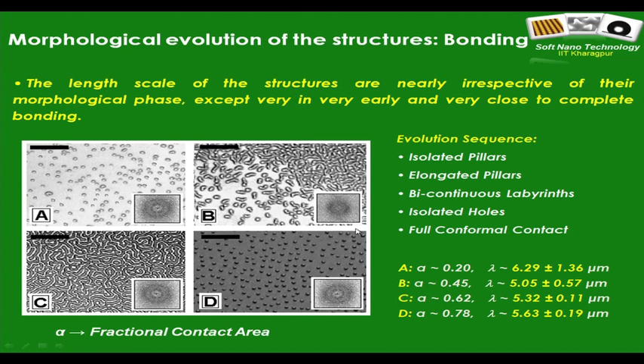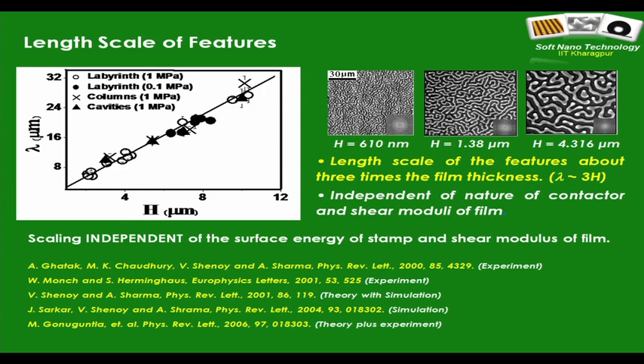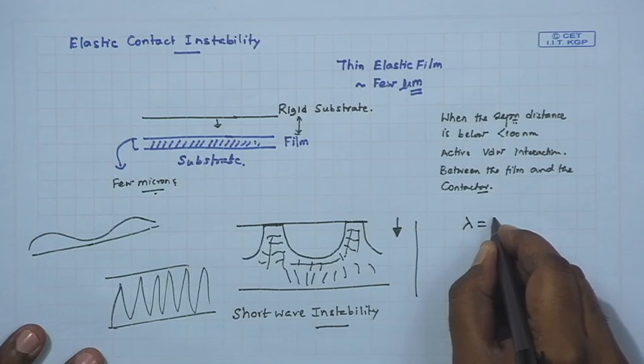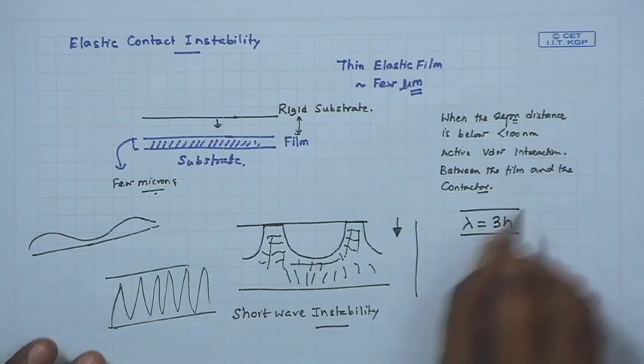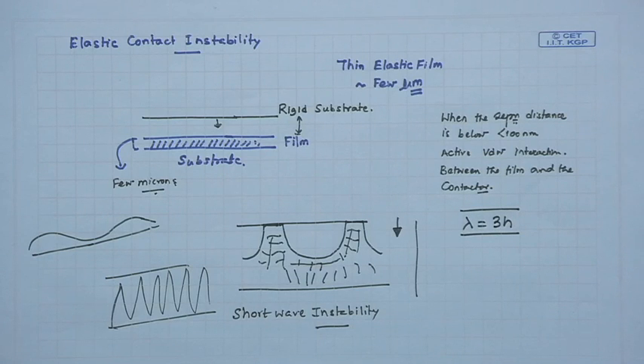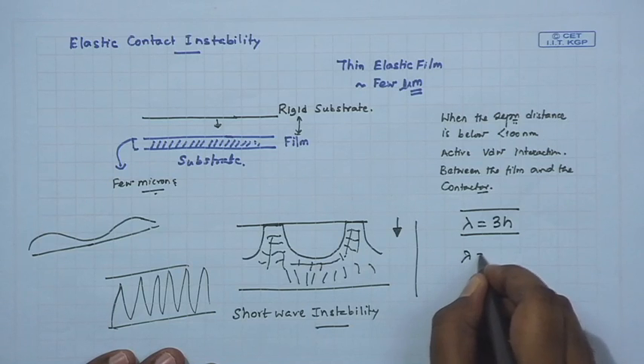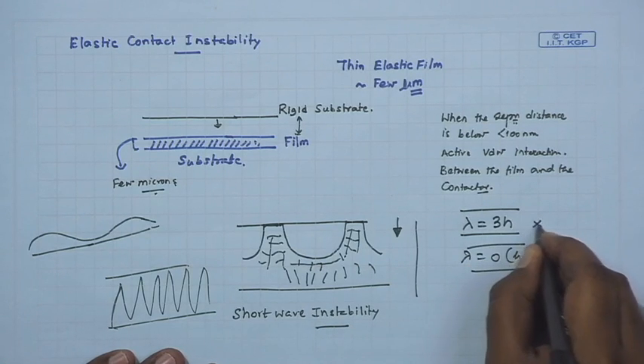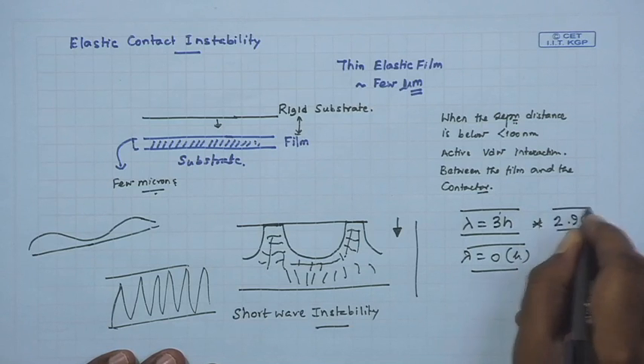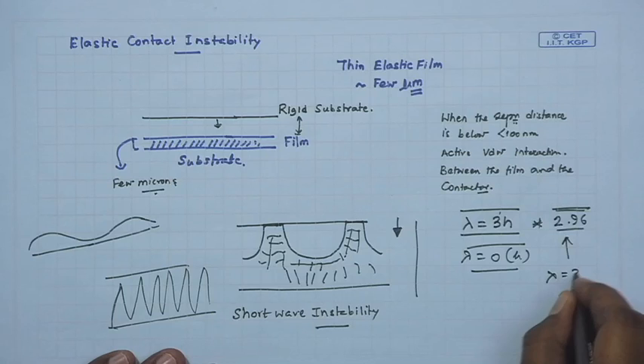But more interestingly, the periodicity of the structures. What is periodicity here? In fact, the structures are random, they're isotropic, but one can do an FFT and find out the periodicity of these structures from there. The periodicity, the dominant wavelength of instability of the structures, is roughly the same. In fact, there has been a significant amount of theoretical work in this area, which shows that for this type of instability, the dominant wavelength of the structures scales as 3 times the film thickness. It's a shortwave instability, so one can argue that lambda is of the order of film thickness, and the exact prefactor, theoretically found, is 2.96, or simply lambda equals 3h.